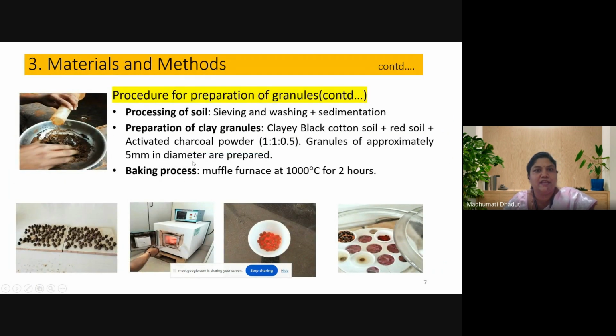So this is the procedure that I was talking about. The sieving and washing, etc., was done, and finally the clay, black cotton soil, red soil, and activated charcoal powder were mixed in a ratio of 1:1:0.5, and then granules of approximately 5 mm in diameter were prepared by mixing all these ingredients using distilled water, and then the granules so prepared were